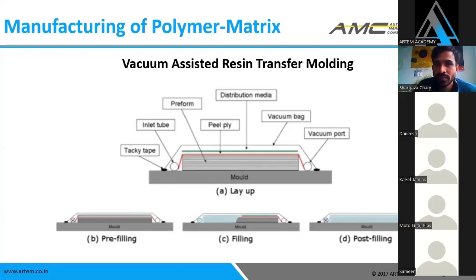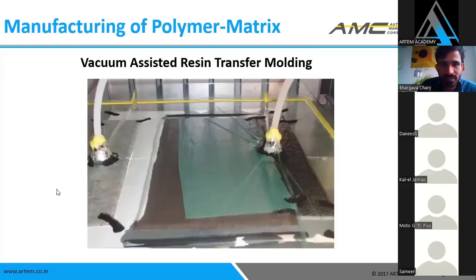So this is one of the polymer matrix, thermoset manufacturing processes. It is mainly driven by the vacuum. The resin is spread all together with the vacuum, so it's a vacuum-assisted resin transfer molding. You can see this is an inlet of the fiber, this is an inlet, and this is a vacuum. Because of the vacuum, the whole section is evacuated and it sucks in all the material. So the resin is transferred completely over the mat, and then it becomes a stronger material, with a binder added.